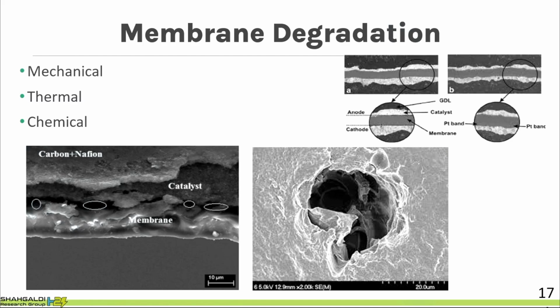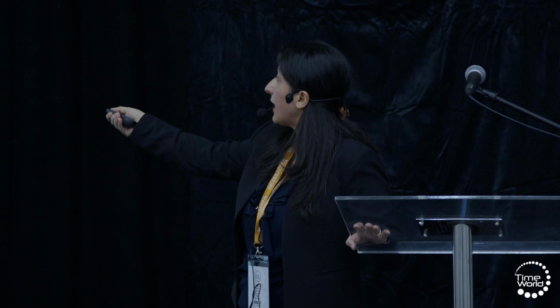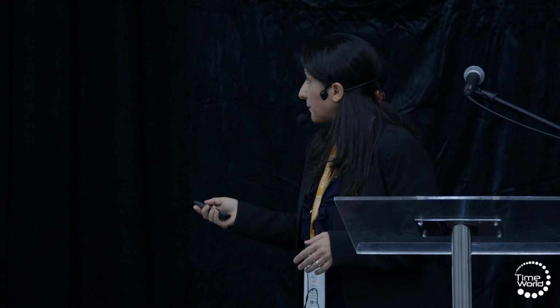And then we have the membrane also, like the catalyst layer, going through degradation. So we have mechanical mode, thermal mode, and chemical mode. Sometimes we have complete delamination of the catalyst layer from the membrane that increases ICR, or, as you see here, we have a pinhole inside the membrane, or on that image on top, here we have membrane thinning. So the membrane becomes thinner and thinner and increases the crossover. So then we don't have good performance inside the cell.